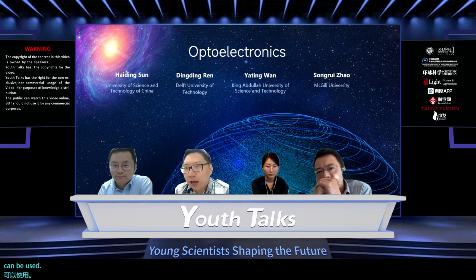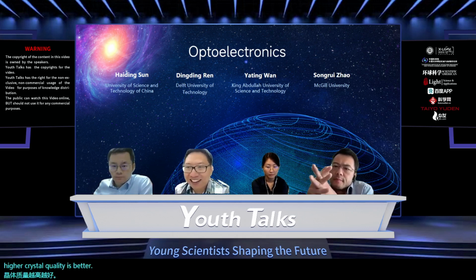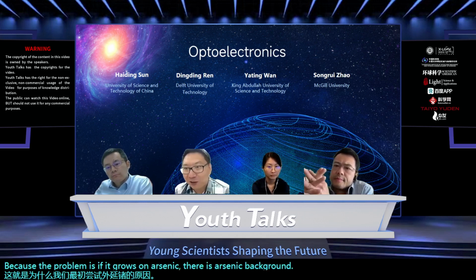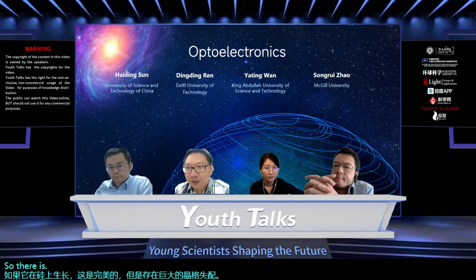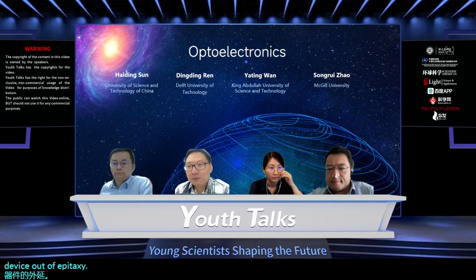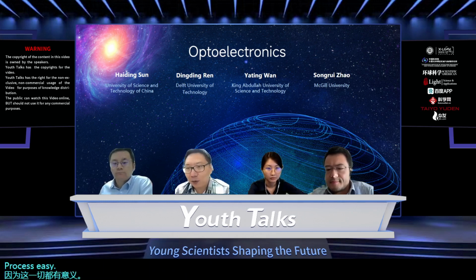Yes. So for longer and longer wavelengths, heavier materials and higher crystal quality are better. That's why we initially tried epitaxial germanium. The problem is if it grows on gallium arsenide, there is arsenic background, right? Also gallium interdiffusion causes a problem. If it grows on silicon, it's perfect, but there's a huge lattice mismatch. So there is not really a good way to do epitaxy for this germanium material. So then you have to think about how to make a device out of it. I think the first solution is to find a way to do epitaxy, because that makes the process easy. But if you don't have that opportunity, maybe we need to think about other alternatives. It's a trade-off, right?